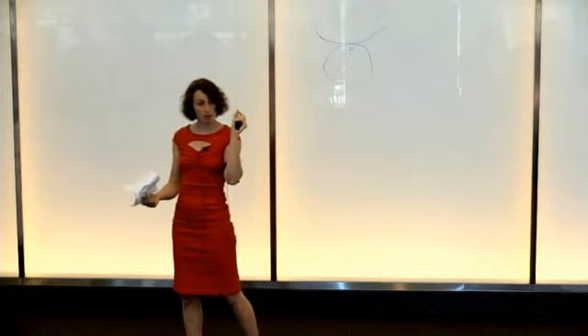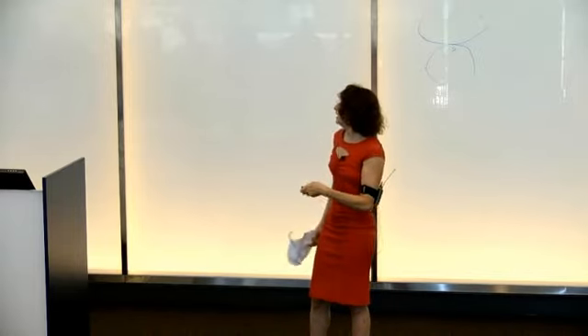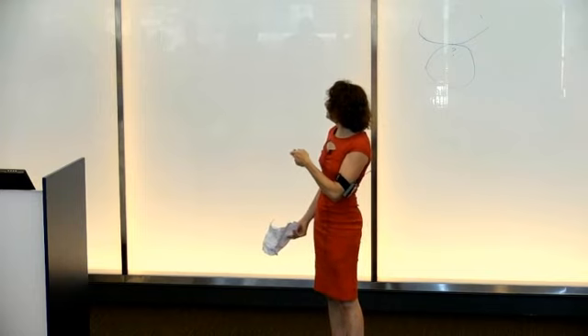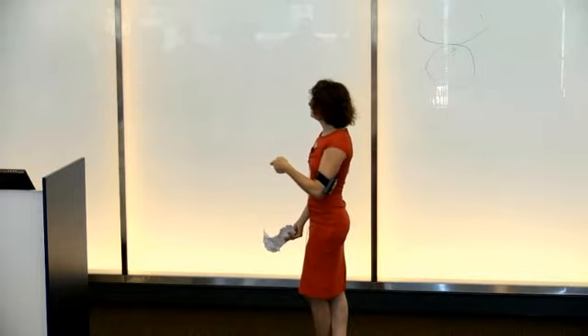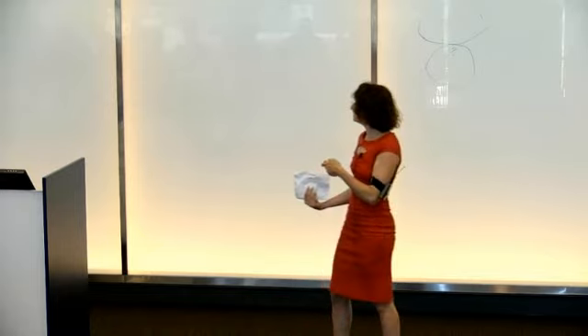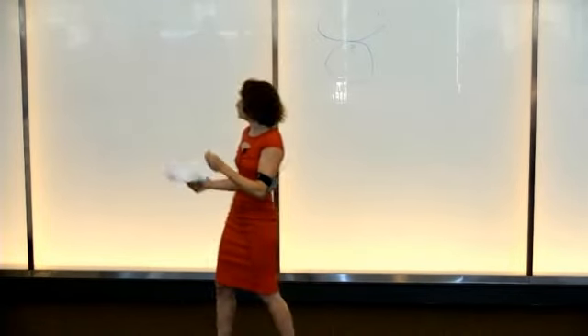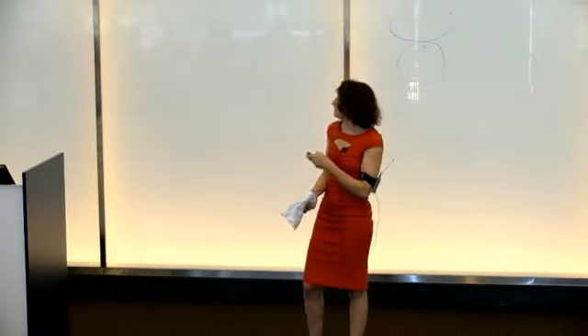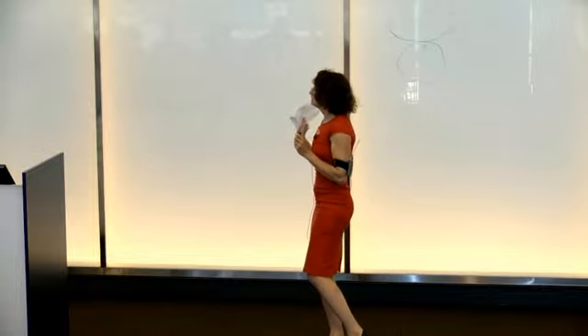This is a good measure for non-locality because it's going to give you 1 if the change was localized in just one node, and it's going to give you n, the number of nodes, if the change is spread out equally throughout the lattice. What we got in this experiment was 12 when we measured the angles. For a 7 by 7 lattice, there are around 100 angles, meaning that 12% of the springs took part in this transitional, configurational change. So that's all I wanted to say.